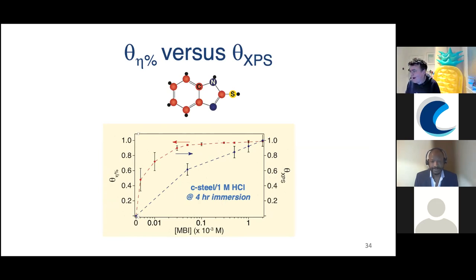But whether the molecule binds in between the sulfate or on top of it, that's a bit difficult to say. But given that we have quite a thick layer, I'd be surprised if there are islands and the molecules are in between. Because remember, it's well inhibited. And so somehow the sulfate will also be coming off, as ferric sulfate will be the sort of corroding surface. So I think the inhibitor is directly interacting with the ferric sulfate. Although we can't say directly from our measurements, we have no lateral idea.